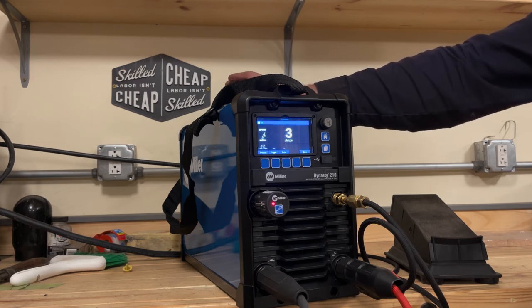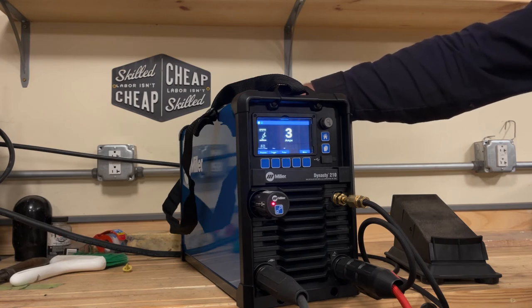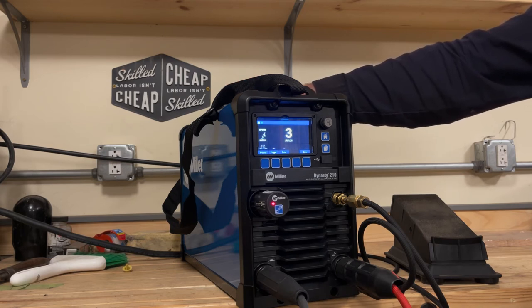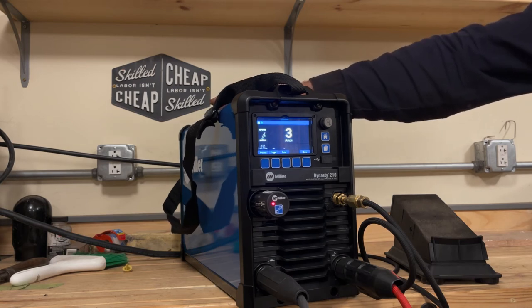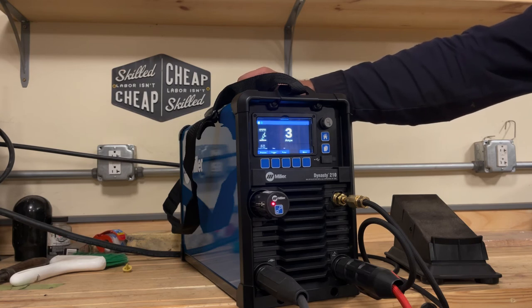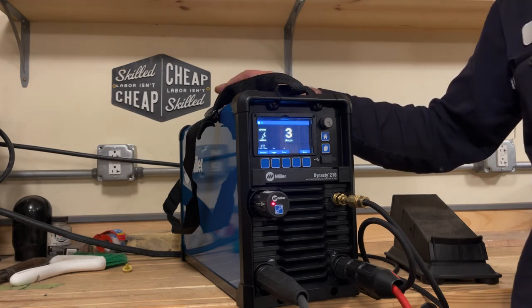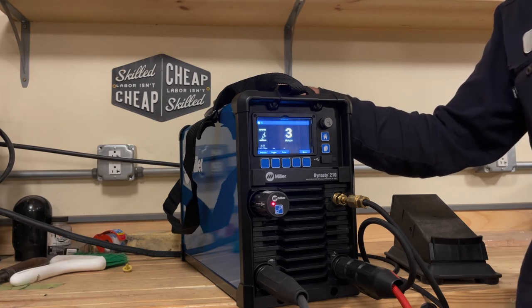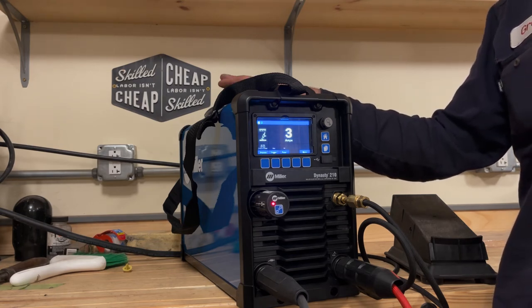Now on aluminum, 200 amps is what I would consider the bare minimum for a TIG welder on aluminum. 200 amps can barely weld quarter inch thick aluminum with proper penetration. And realistically, you'd have to preheat the aluminum at 200 amps to get proper penetration. So 3/16 thick aluminum is about the limit of what you'd want to weld without a preheat with a 200 amp class machine. And that's why when you start seeing Miller's higher amperage output, the Dynasty 280, 300, the 350 and the 400, all of those and even bigger yet are for welding really thick aluminum. That would be the primary reason why you would need that level of output is for the aluminum end.